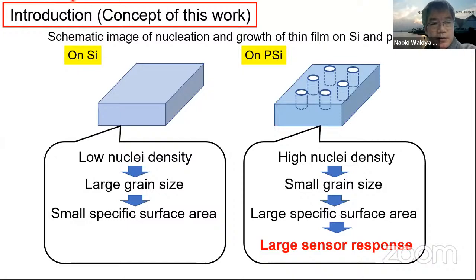So at first, I'd like to explain the concept of this work. This is a thin film on silicon substrate, and this is a porous silicon. If we deposit thin film on this substrate, this is a schematic image of nucleation and growth of thin film on silicon and porous silicon. On silicon, this is a nuclei, and there is a low nuclei density, so it will grow like this. So large grain size is realized. So it means a small specific surface area.